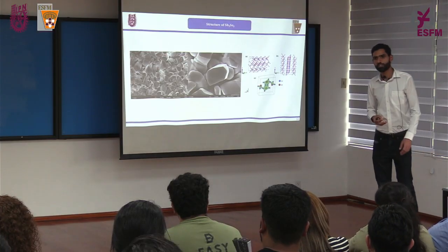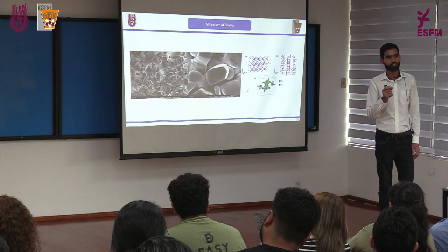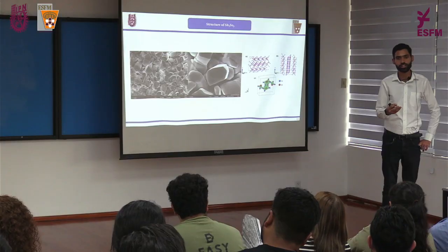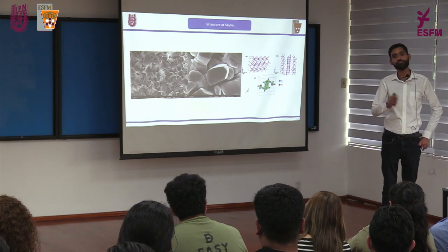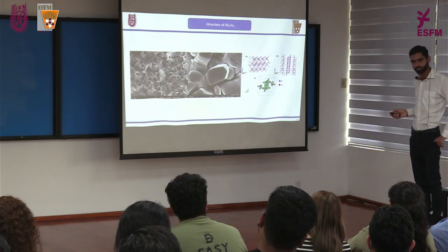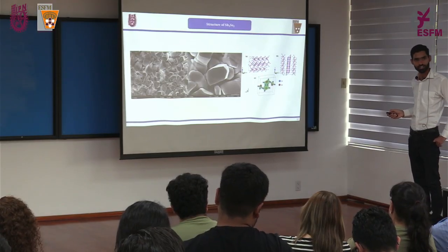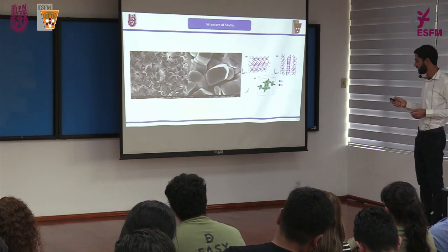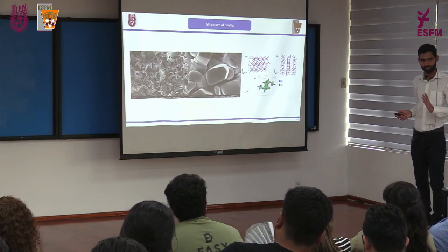The main problem related with this material is the structure. This material is, we can say, very choosy, a very moody material. It gives us output if it is appropriately made, if we have a ribbon-like structure vertically, not horizontally. If we have the other kind of structure in our material, we will have a response, but not enough, not good. We need to have vertical ribbon-like structures in our material.